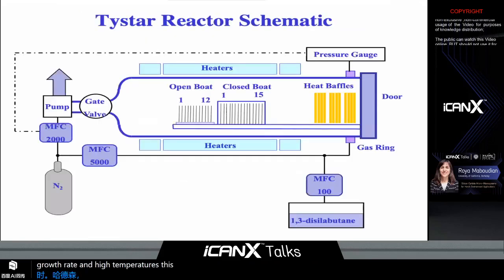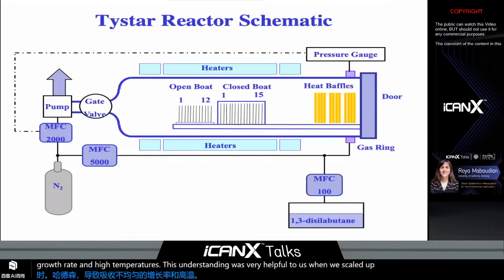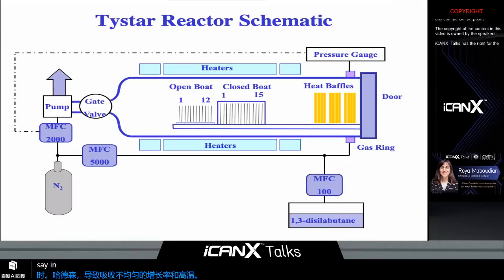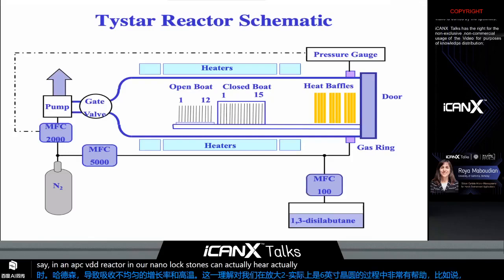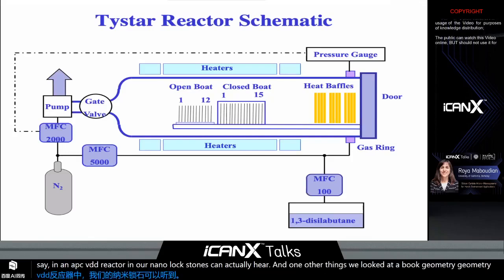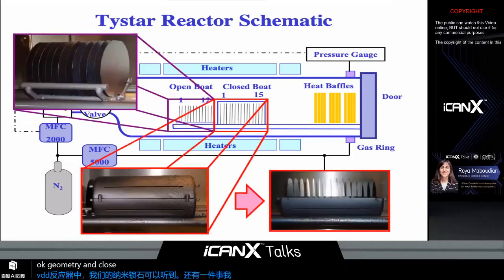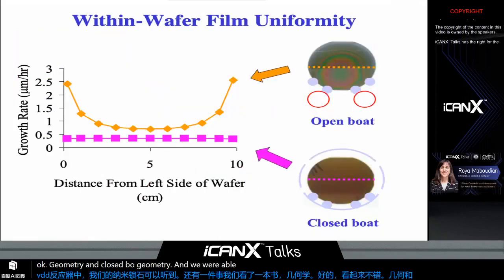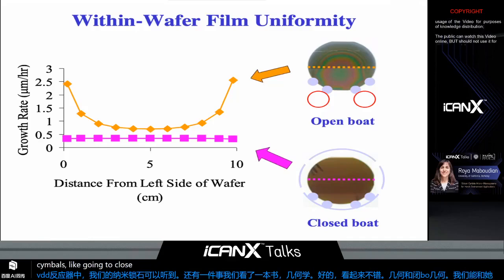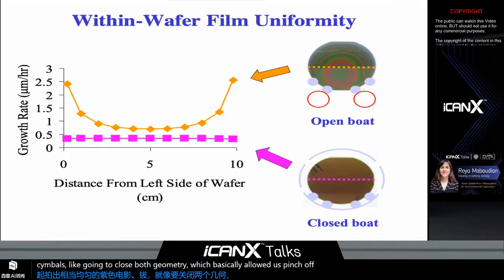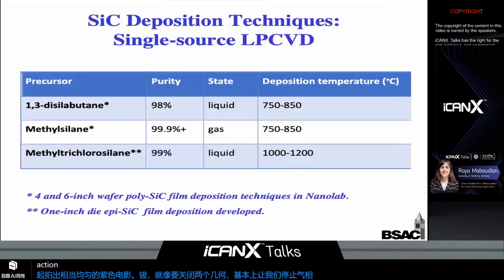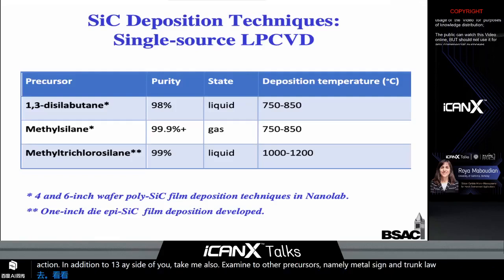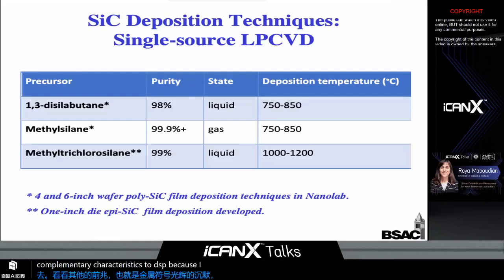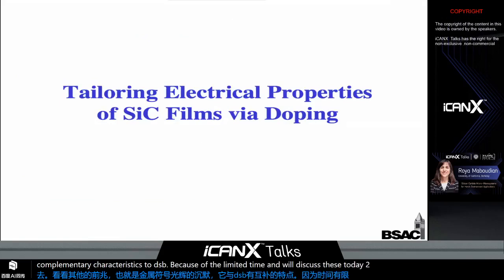This understanding was very helpful to us when we scaled up the process to actually 6-inch wafers in an LPCVD reactor in our nanolab, shown schematically here. Among other things, we looked at two boat geometry, open boat geometry and closed boat geometry. And we were able to obtain fairly uniform films, shown here in purple symbols, by going to closed boat geometry, which basically allowed us to pinch off the gas phase reaction, the second reaction pathway. In addition to 1,3-disilabutane, we also examined two other precursors, namely methylsilane and methyltrichlorosilane, which have complementary characteristics to DSB, but because of the limited time, I will not discuss these today. And move to the next part.